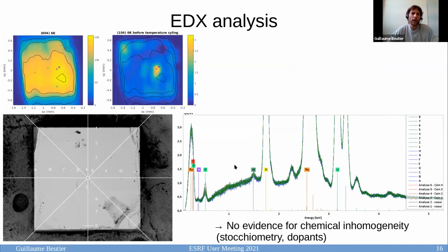So to complement this analysis, we did some EDX analysis in the lab to see if there was a departure from stoichiometry or some contamination from other elements. Basically we did this analysis along two perpendicular lines, at points separated by 150 microns each time. You can see all the scans are overlaid together, and there is basically no significant difference as much as we can say with this technique. So there is no obvious inhomogeneity from the chemical point of view.